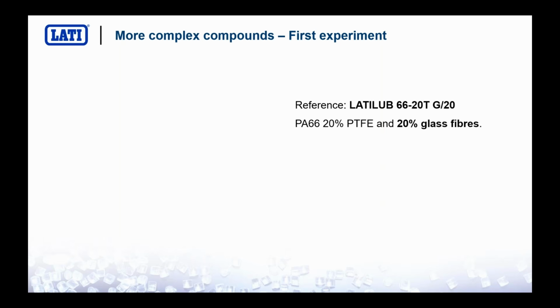We also performed some extra tests in order to see if the same additives, which work in a good way for a polyamide 66 plus PTFE, can give the same advantages with another material, for example, with glass fiber. This is our material, our polyamide 66, LATILUB 66-20T G/20, which is our polyamide 66 plus 20% of PTFE and 20% of glass